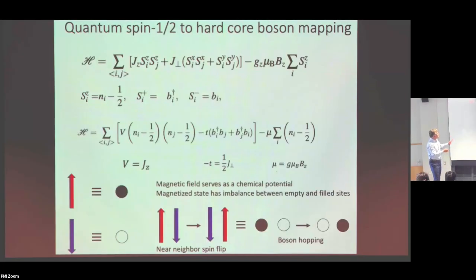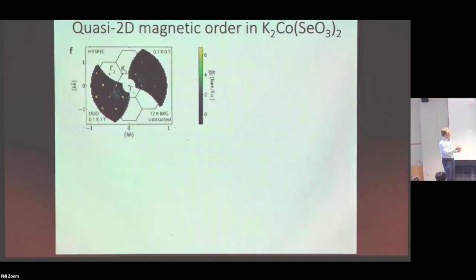And let me just go back once more to this. I forgot to say that the Zeeman term maps onto a chemical potential for the bosons. And so I can actually vary the chemical potential by just changing my magnetic field. That's a wonderful variable to have as an experimentalist. You just have a dial to adjust it. And so this is really gorgeous. I'm going to be able to change the density of bosons on the lattice just by changing the magnetic field. So this is in 0 field, so that would be 0 chemical potential. And this is when I put a big field on and I get into this 1/3 magnetization plateau. And this is what the diffraction looks like. I've subtracted off the high temperature diffraction from all the sample holder and all these other things. So all that's left is the magnetic component of scattering.